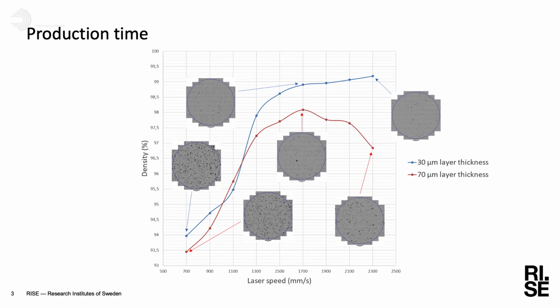Right, and I know that you have this fantastic graph showing the printing speed and how that can be affected by the printing parameters. What kind of speed increases have you been looking at? So we've been looking at increasing the laser speed to up to 2,500 millimeters per second almost. We decided on a window where we were comfortable in managing to print the parts. We were also looking at different layer thicknesses, so using the standard of 30 micrometer layer thickness and increasing it to 70 micrometer layer thickness. That could even be increased more, up to 90 micrometer layer thickness if we wanted to, but we wanted to stay in a comfort zone, so to say, to be able to print good enough parts. So we were able to print these parts with quite high density, but not good enough.